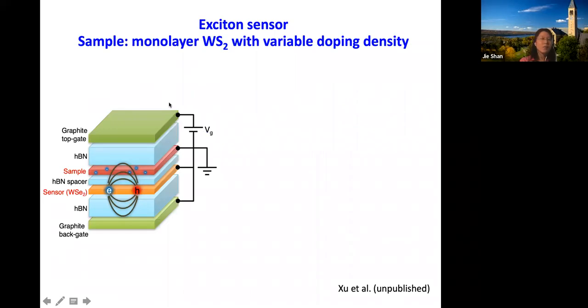And this is the device schematic. Here is our sensor layer. To electronically separate it from the system we want to measure, we put an hBN spacer of a nanometer or that order. And then this is the sample layer, and we can have gates to charge, or dope, this sample layer.